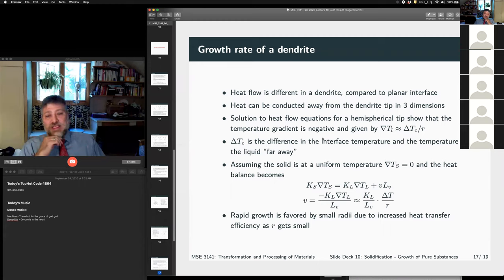So this delta TC that we showed before is the difference between the interfacial temperature and the temperature of the liquid far away, right? So if we assume that the solid is at a uniform temperature, there is no temperature gradient in the solid. So there's no heat conduction in the solid. Essentially, everything is going through the liquid, right?